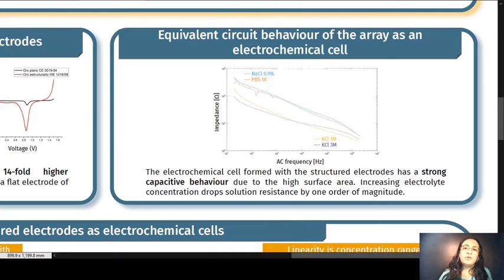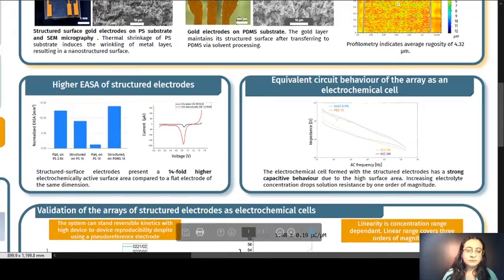Next, we wanted to understand what was the electrical behavior of the cell conformed by the structured electrodes. To do this, we performed impedance spectroscopy. Here we found that the impedance dropped as the AC frequency increased, which means that the electrochemical cell is behaving as a capacitor. Maybe this is due to the high surface area of the electrodes.